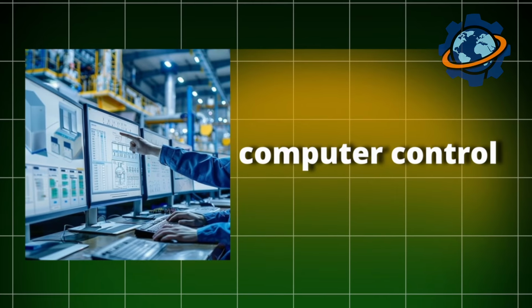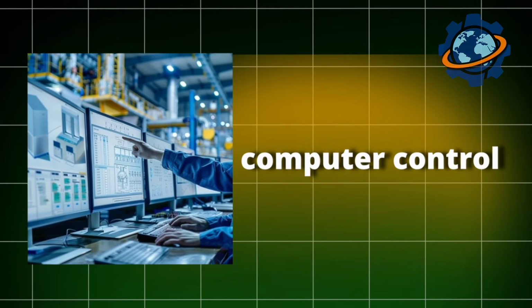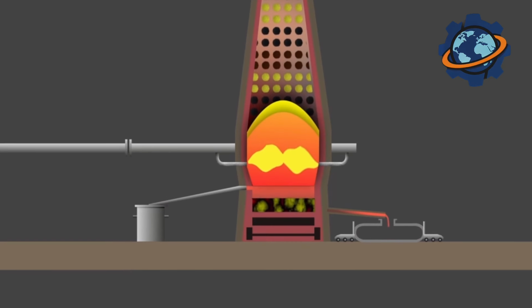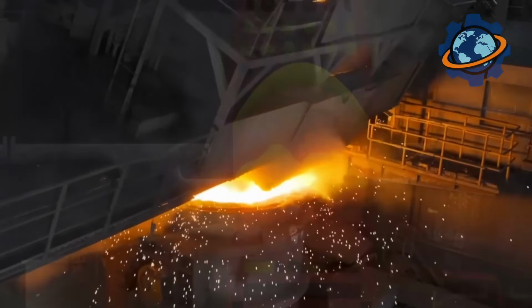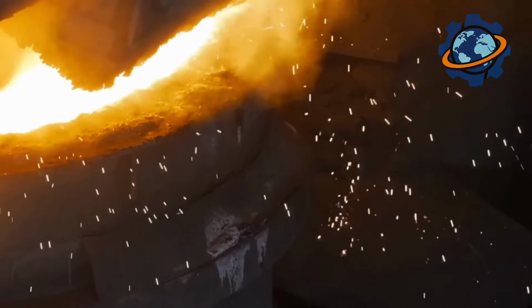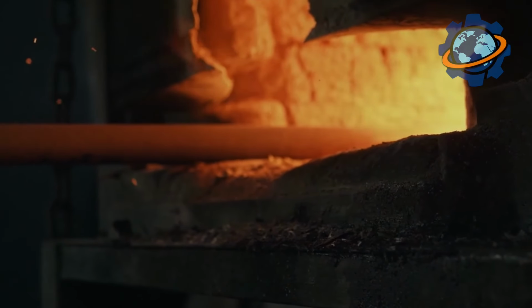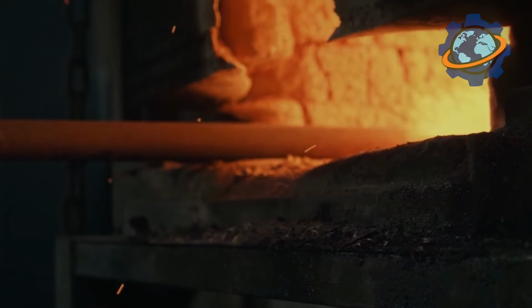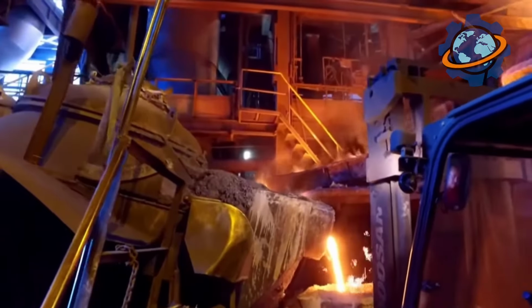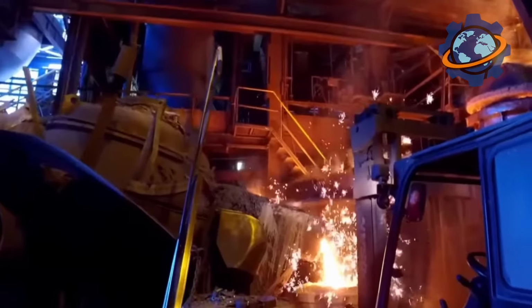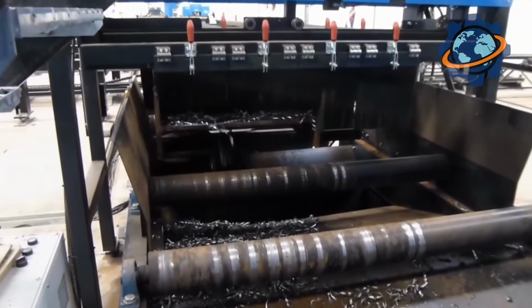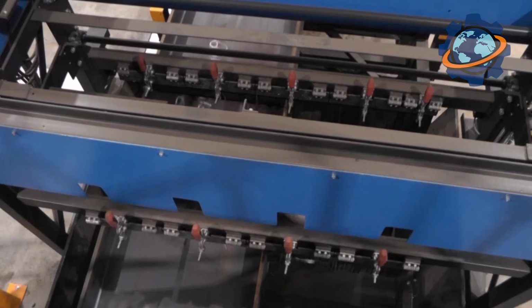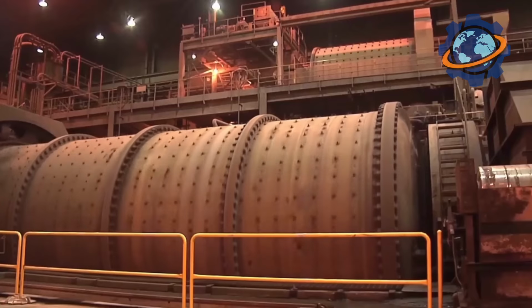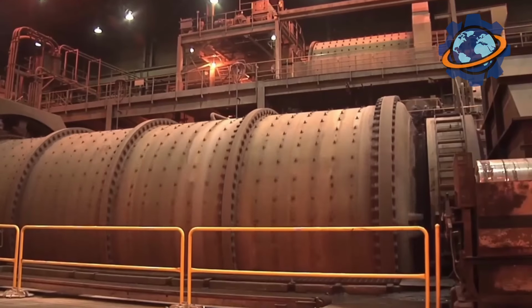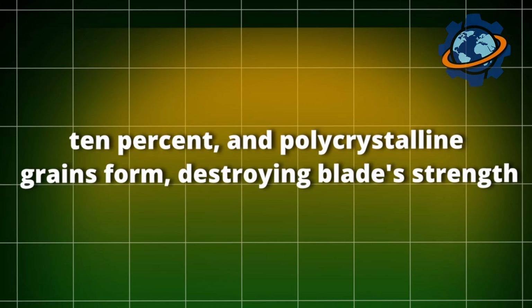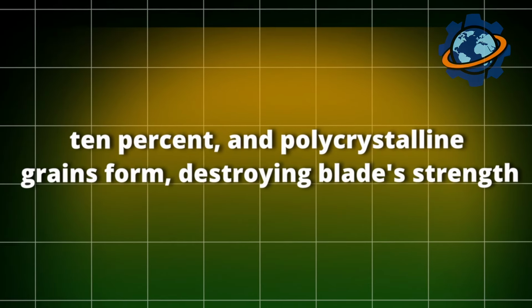Slowly, incredibly slowly, a computer-controlled mechanism lowers the mold through the furnace at speeds of 6 inches per hour. Picture watching paint dry, then slowing that down tenfold. As the mold descends, metal solidifies from bottom upward in a razor-thin freezing front. This directional cooling forces crystal growth in one direction only, upward, eliminating horizontal grain boundaries where cracks normally form. The process takes 14 hours for a 4-inch blade. Rush it by even 10% and polycrystalline grains form, destroying blade strength.